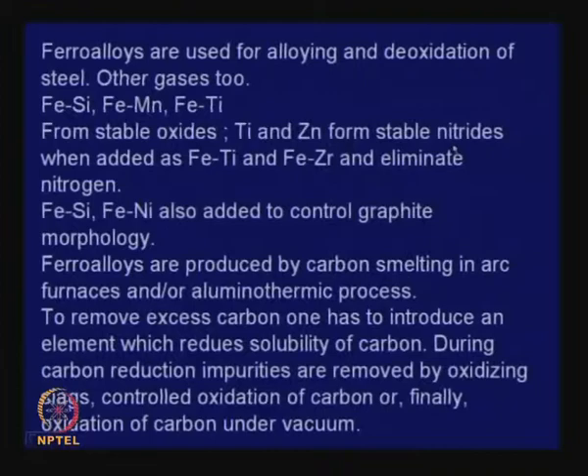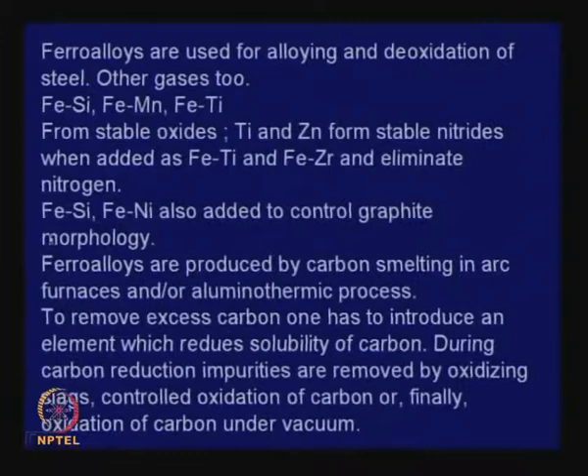Titanium and zirconium form stable nitrides, whereas ferrosilicon, ferro-manganese, and ferro-titanium are usually used as deoxidizers. If you want to remove nitrogen, ferro-titanium and ferro-zirconium are used. Ferrosilicon and ferronickel are also added to control graphite morphology in cast alloys.